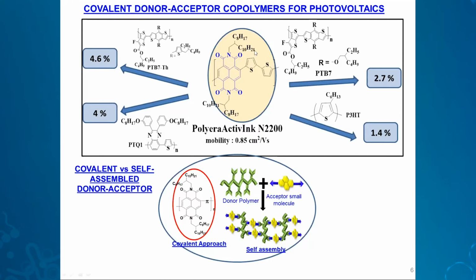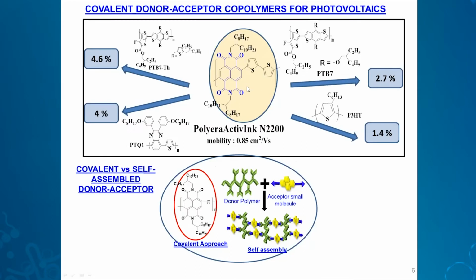This is one of the widely used acceptor type polymers because of its very high electron mobility, like 0.85 centimeter square per volt second. And when this polymer is used as the acceptor along with other donor type polymers in an all-polymer solar cell, several very good power conversion efficiencies have been obtained. This data is a little old. Now higher power conversion efficiencies have also been obtained. One of the very good efficiencies has been obtained with this combination of N2200 as the acceptor polymer with PTB7-Th as the donor polymer.